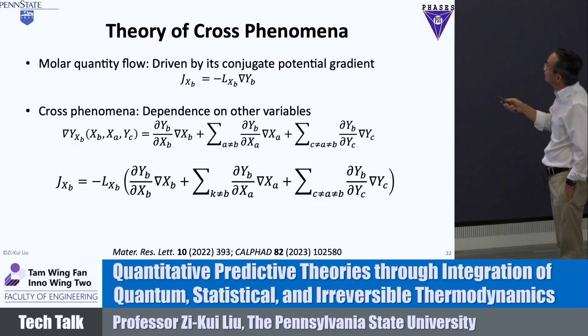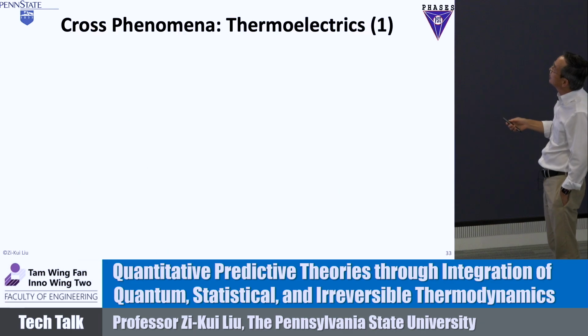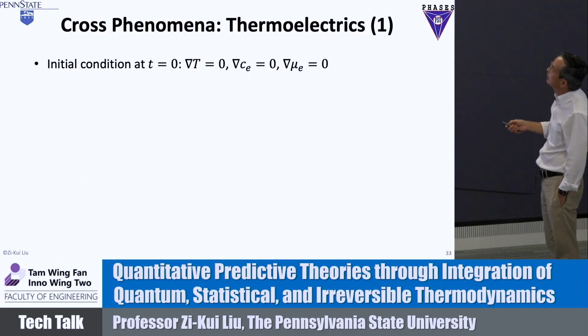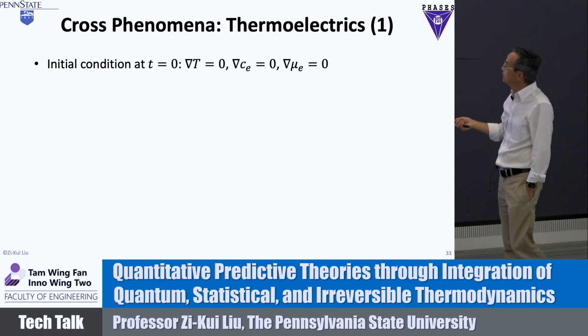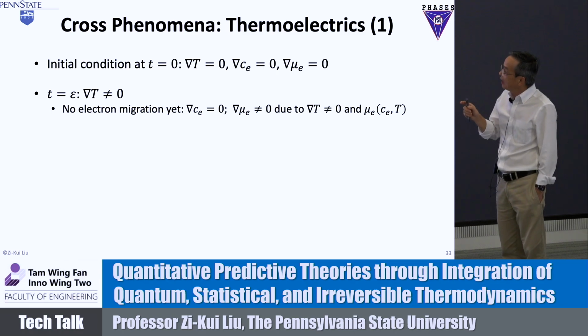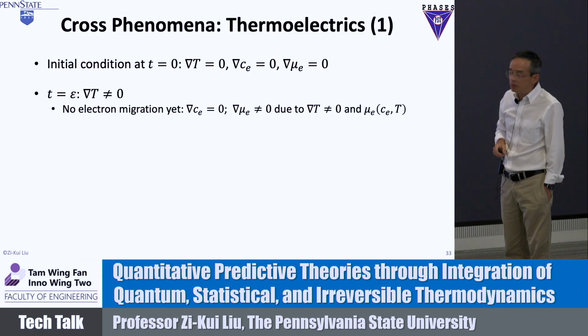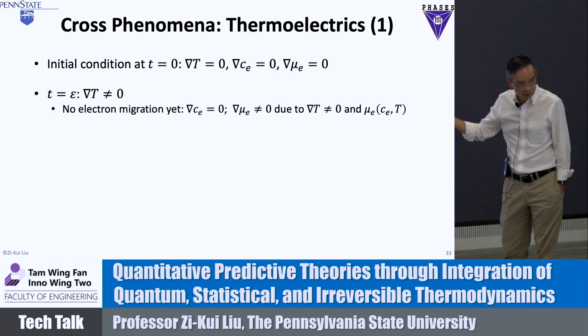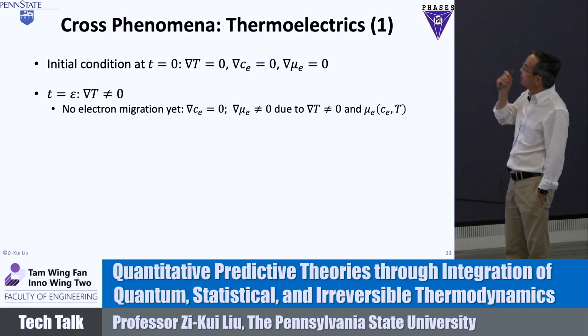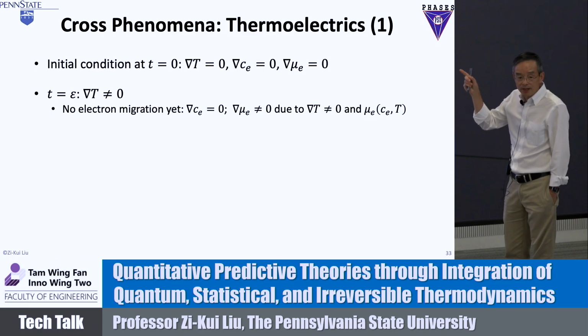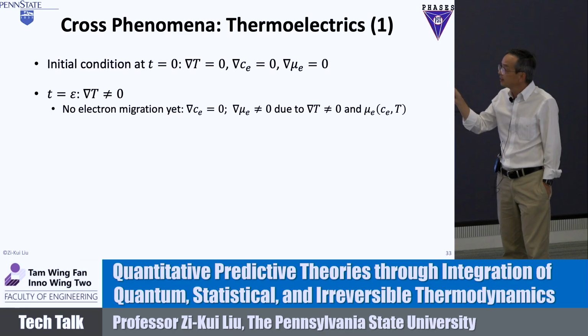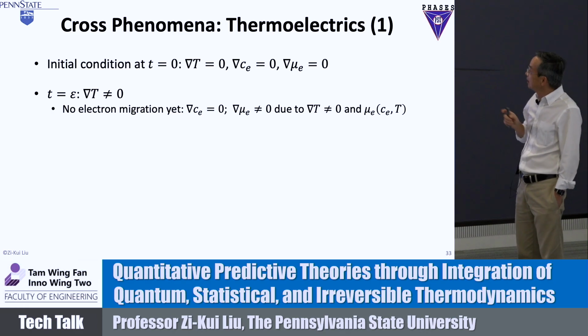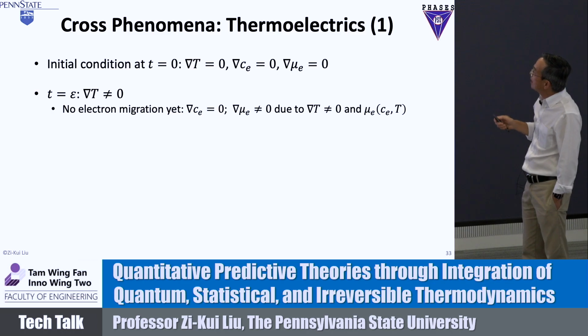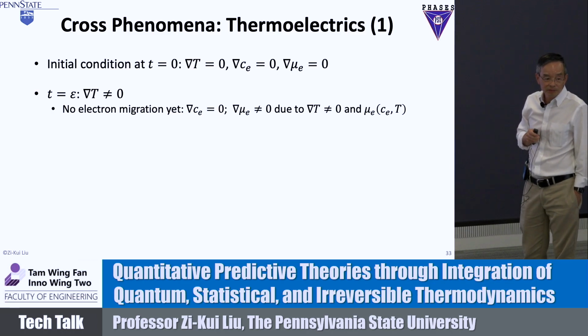So basically, we can give an example. The example we show here is a thermoelectric. At the initial time, there is no temperature gradient, no concentration gradient, no chemical potential difference. Now, if you add a temperature gradient in an infinitely small time, there's no electron migration yet, so the concentration gradient of electrons is still 0, but the chemical potential balance is not there anymore. The temperature gradient gives heat flow. That means now the electron is going to move, because now you get a potential.